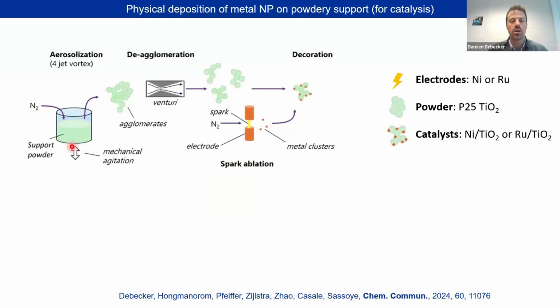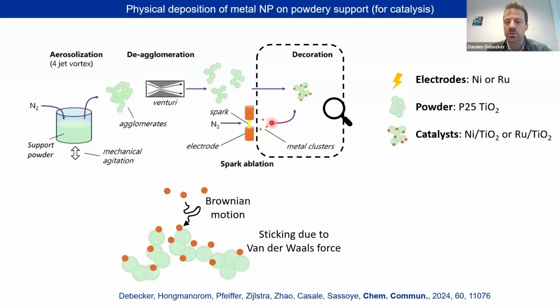In a scheme, it looks like this. We have our support, we aerosolize it, those particles are carried away, we use a trick to de-agglomerate them, and then we bring them very close to the spark itself, where they are decorated by the nanoparticles, and then we collect them. In our case, we worked with titanium dioxide as the support, and we worked with a nickel electrode as the first example. How do the particles get attached to the support? Well, it's simply Brownian motion and van der Waals forces. There's nothing more. They are just very close to each other, and we hope to see them sticking to the support.